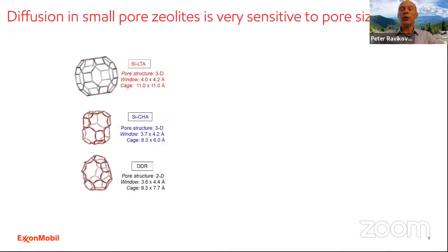So when we're talking about small-pore zeolites, we talk about materials of this type, and these are some examples of these zeolites. They usually have sufficiently large cages where we can adsorb molecules, but these cages are separated by narrow windows. Let me make my pointer laser. So these are windows. For example, this is an 8-member ring window consisting of 8 oxygen atoms. And these windows are pretty narrow, and they can be controlled very well by synthesizing different materials.